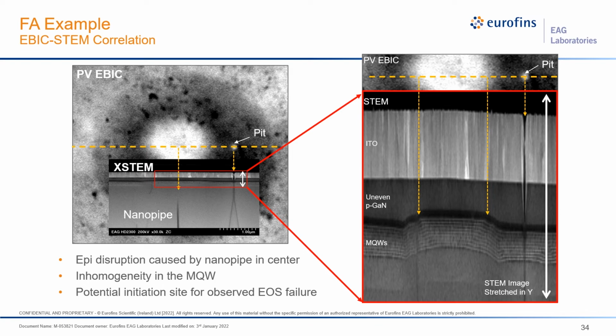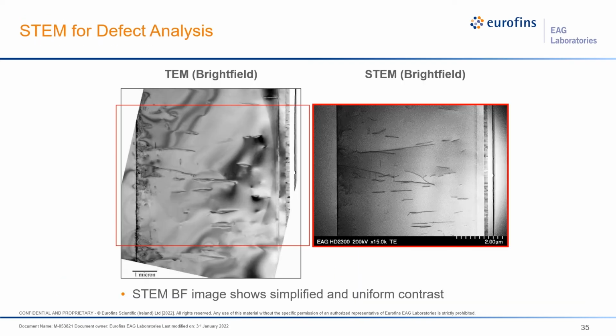So defects like this then become very interesting. So what is it about this particular defect? In this case, it's two dislocations that come together that form this V pit. So something about it disrupts. Obviously, the nanopipe is causing disruption in growth, and you get this quantum well disruption. So the crystal itself is growing at different rates because of the environment around this particular defect. But the same thing is true about this dislocation annihilation, this combination of two defects here to the right. So in a lot of cases, we need to then use STEM to look at defect analysis. So how can we sort out the different types of threading defects?